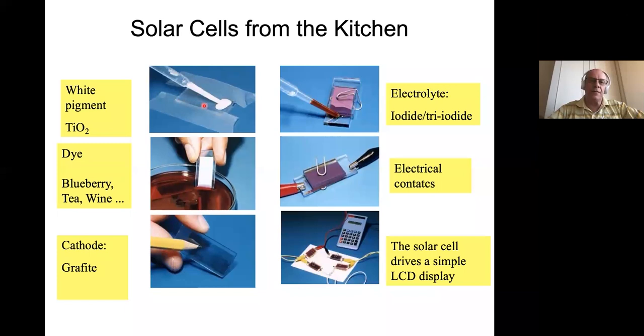One is that it makes a certain thickness of the TiO2 layer, and it also forms a contact, and we can take away the scotch tape and attach our contact. Then it's a step here, which is a heat step, where we can use a burner if you have a classical chemistry lab, or a strong heat gun, for example.